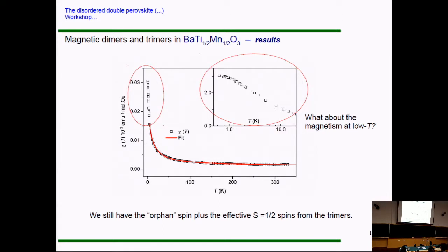Because if we look back at what we are saying, it is essentially that at high temperature some of the spins will form dimers. They will be frozen, right? They will no longer contribute to magnetism. The exchange coupling is pretty high. Then you go a little bit lower in temperature, and you still have the trimers, whose ground state will contribute with an effective spin 1/2, and you still have the orphans, right? So you still have a lot of magnetism in the system. So essentially, this is the question that should be answered, and then we started investigating that.